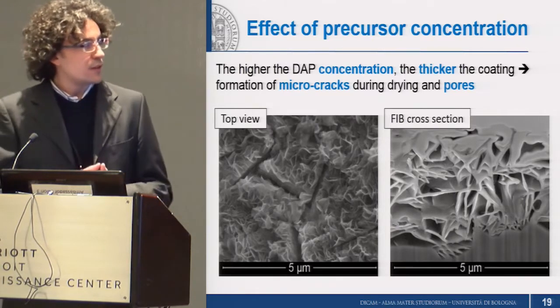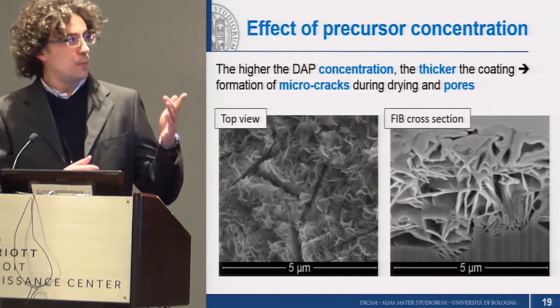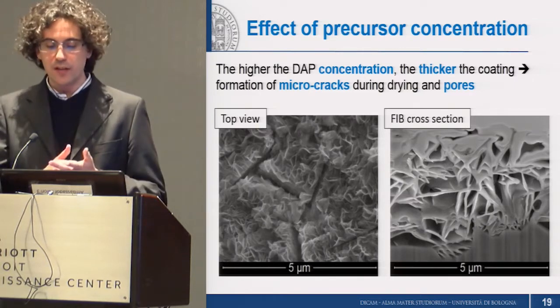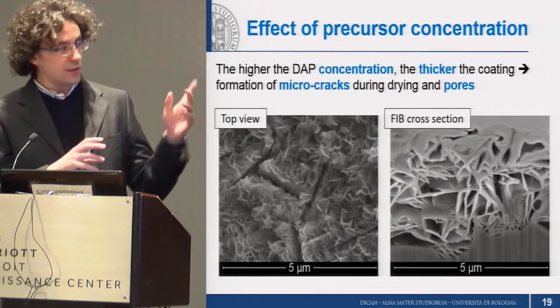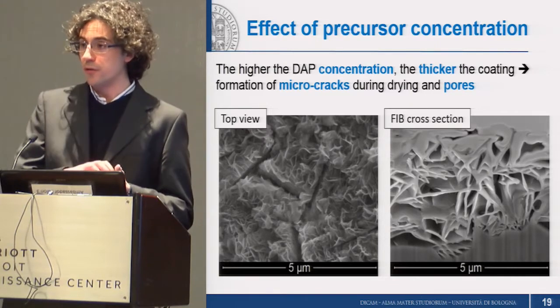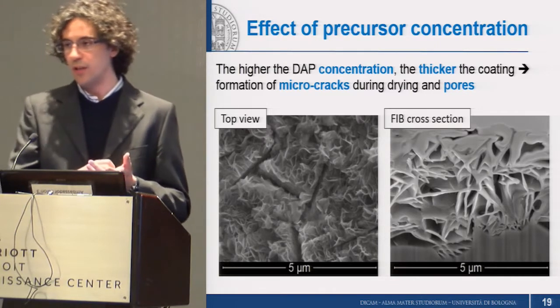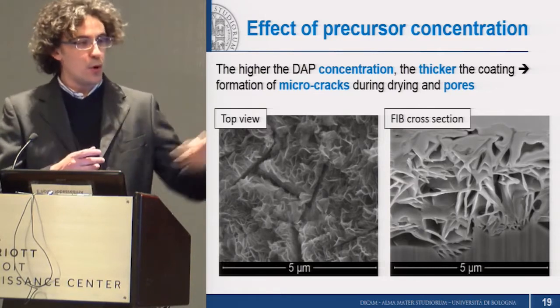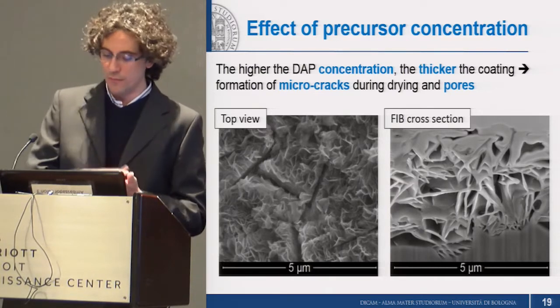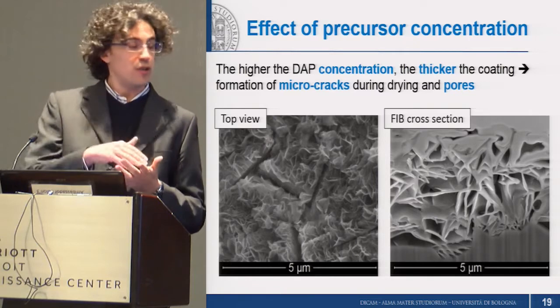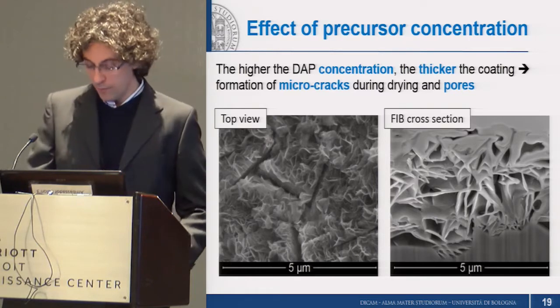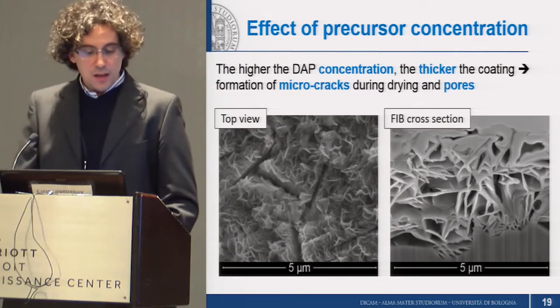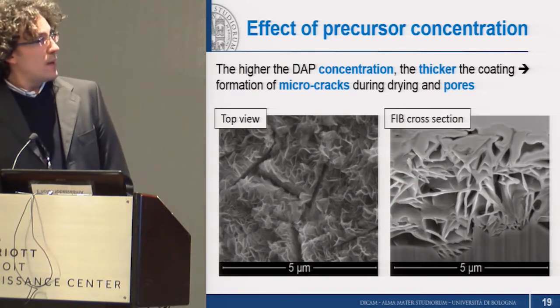And as we were recently able to observe also by focused ion beam in cross-section, the coatings that form in these conditions are also porous, which of course is a problem because micro cracks and pores may allow rain, so the acid, to reach the substrate, which would be bad for our purposes. So to avoid this problem,